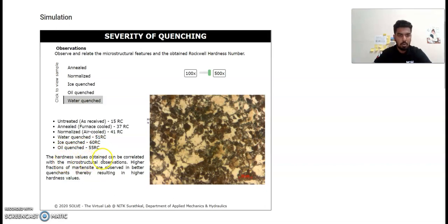The hardness values obtained can be correlated with the microstructural observation. Higher fractions of martensite are observed in better quenchants, thereby resulting in higher hardness values.